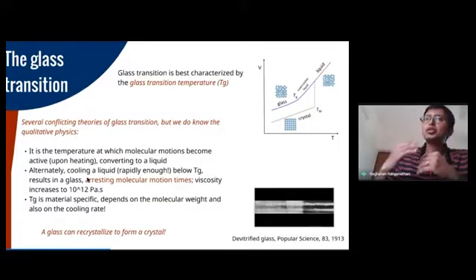So an alternate picture is that when you cool a liquid, of course, rapidly enough so that you follow this non-equilibrium protocol, and you cool it below Tg, what we do is we completely arrest the molecular motions, and this leads to glass basically behaving like a solid, and the viscosity increases by leaps and bounds, and it becomes fantastically large. It becomes about 10 power 12 Pascal seconds. So compare that to a liquid that has a very low viscosity, maybe of the order of a few Pascal seconds.